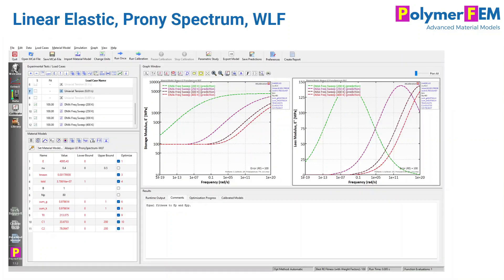Perhaps we can do even better, but before getting there, let's look at the predictions of this model for something we don't have data for — a virtual frequency sweep. The frequency sweep predictions at different temperatures show a very wide spectrum of responses, spanning roughly 10 to the 20 down to 10 to the minus 19, shifted left and right based on the WLF equation. The model requires such a broad spectrum because it's missing the temperature dependence of the elastic response.